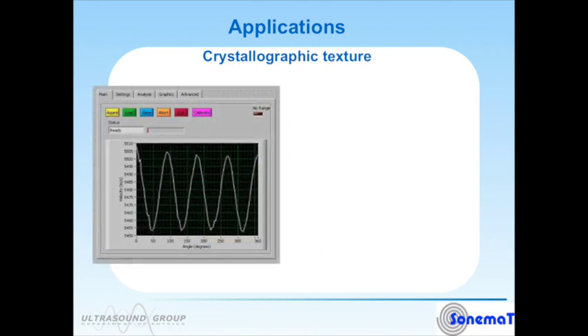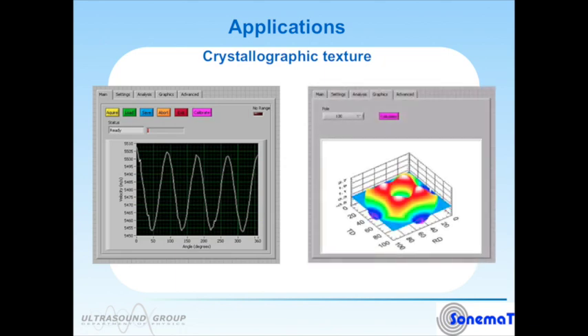We can plot a variation of velocity of this particular guided wave as we rotate, and these measurements can be done in a matter of seconds. If you look at the numbers of the change in velocity on the plot on the left, you can see it going from 5505 meters per second to about 5455 meters per second. That's the maximum variation. It's evident in this experimental data that the actual measurement precision is much, much higher than that. We can only achieve this because of the non-contact nature. It's very difficult to generate this type of wave in a controlled way without using an EMAT.